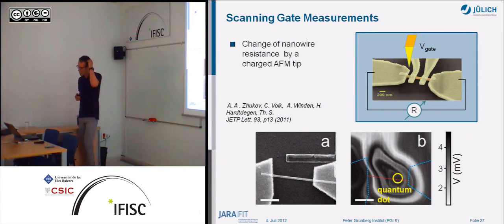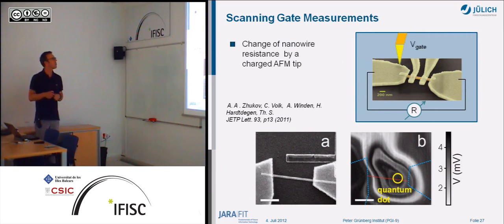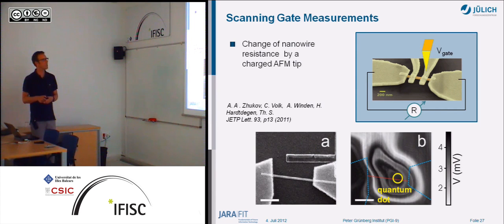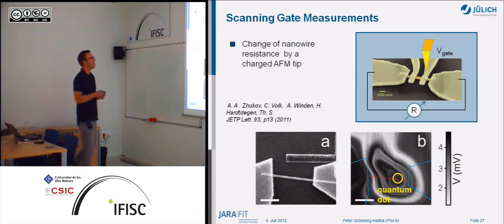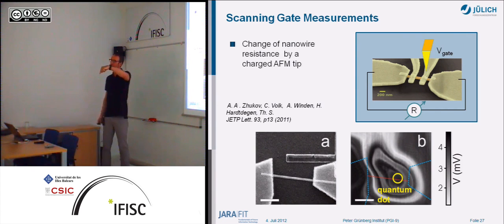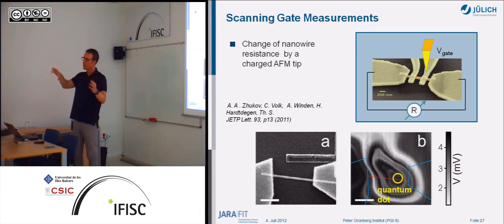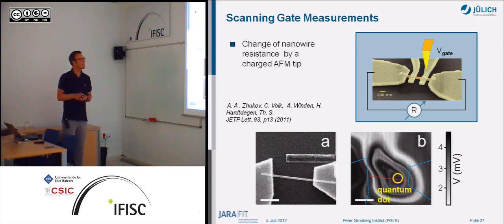And actually you can do that in more detail if you do a so-called scanning gate technique. By scanning the gate here, it's like this with a tip of an STM or an AFM tip, a conductive AFM tip, you can put a voltage here, and by scanning this tip along the nanowire, you can change the potential in the surrounding of the nanowires, and this tells you something about the transport here. So if you measure the resistance here, the resistance is influenced by the potential of the tip. And if you do this systematically, you can even identify where the quantum dot is.